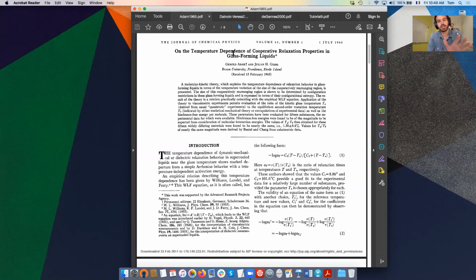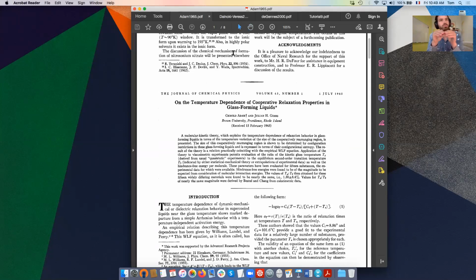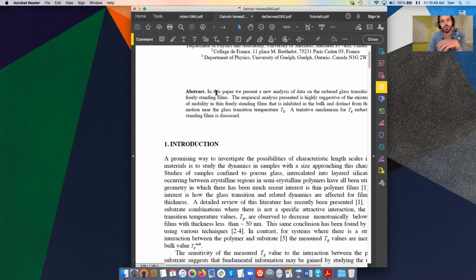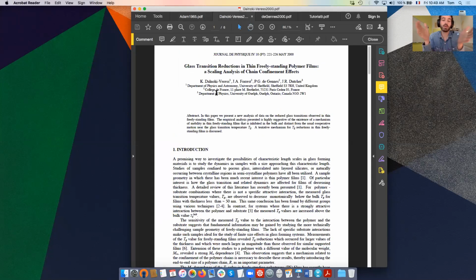As you will see in this glass transition problem, there is some microscopic length scale that we call the cooperative length, which is the region in the sample where you would have a relaxation. So you have a certain size in the system that is called the cooperative size. And an idea emerged afterwards, which was the following. If there is a microscopic size in the system, perhaps by reducing the material dimensions, you might end up reaching this size and measuring some anomalies. And this has been done with thin polymer films in the group of Dutcher by, in particular, Carrie Dalnoki-Veress and James Forrest, where they studied the glass transition in confined settings.